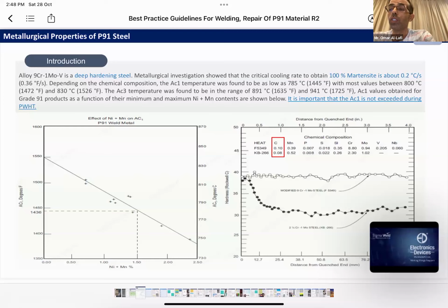It's very important to notice that the AC1, or the lower transformation temperature, is a function of minimum and maximum nickel and manganese content in the material. So the tempering of the weld metal is done close to this temperature, the AC1 temperature, and the content of nickel and manganese can lower this transformation temperature and can bring our PWHT temperature above this critical line. It should be noted that we shall never exceed this line during our heat treatment. We'll speak more about this, but this graph on the left side shows how nickel and manganese content can lower the transformation temperature, or AC1 temperature.